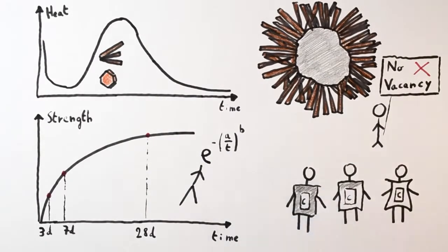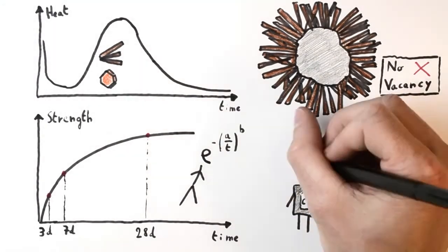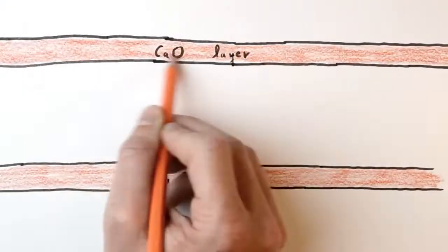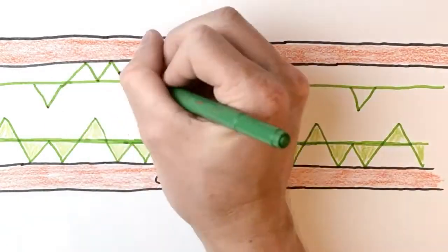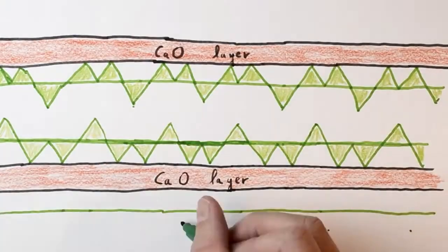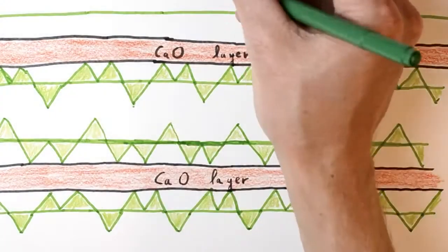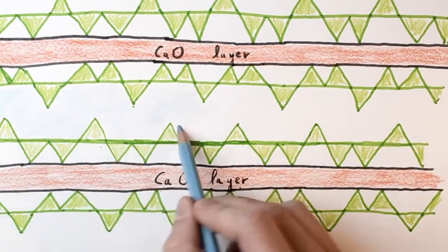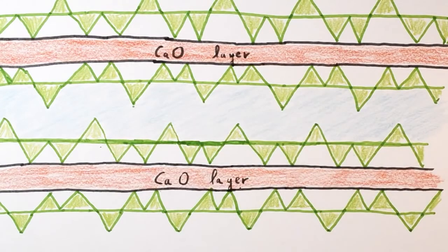The exact atomic structure inside the needles is still the subject of debate between cement scientists. It does not show a well-defined crystal structure, but rather a nanocrystalline region where short-range order exists. The features are somehow similar to the 14 angstrom tobermorite mineral made of calcium oxide backbone layers, flanked by silicate tetrahedra on both sides, and containing significant amounts of water in the interlayer regions.